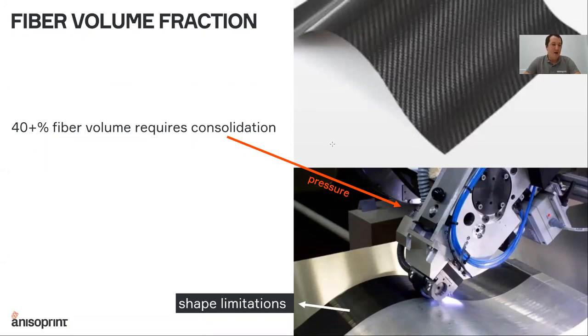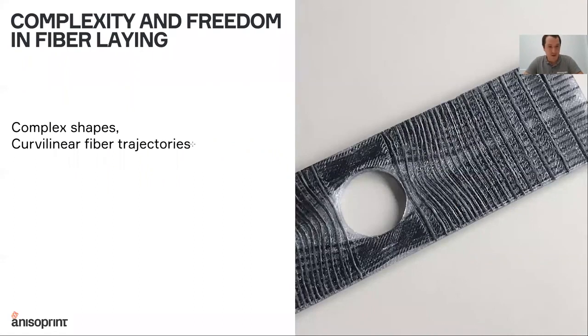So with the co-extrusion, we are not getting to very high fiber volume fraction, but by being able to vary it and by not having a necessity to apply pressure, we are able to print very complex shapes with no post-consolidation required, and good material properties and low porosity with no extra pressure applied. So this gives us a lot of flexibility, and flexibility is the most important word here, and that's what we are trying to bring with our composite fiber co-extrusion technology.